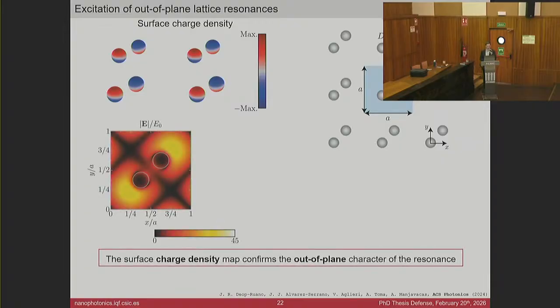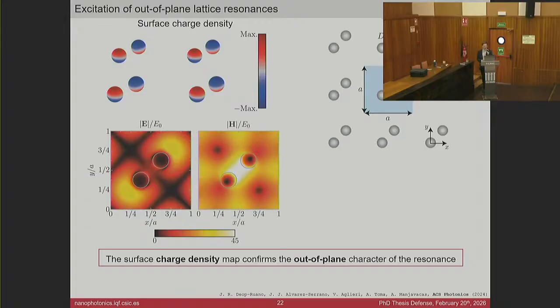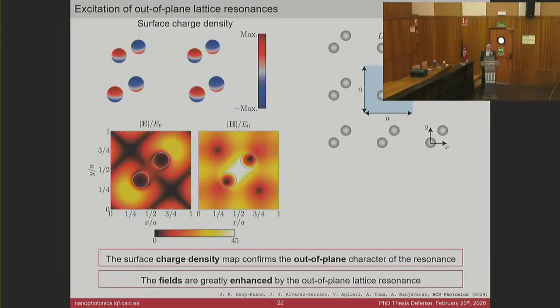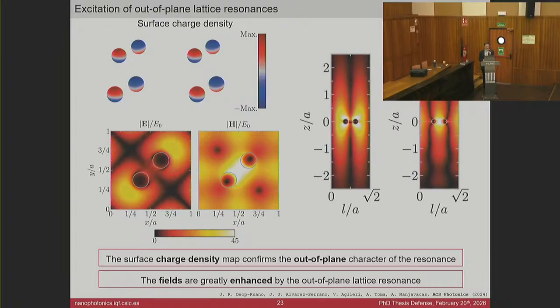I also use these finite element method simulations to study the electric field enhancement and also the magnetic field enhancement, and we can see that the fields are actually greatly enhanced around the whole unit cell. Because of this opposite orientation of the dipoles, in the case of the electric field this is minimized, but in the magnetic field it is maximized, and it actually attains really large values. We also observe that even if we move far away from the plane of the array, 2 periods, for example, we still observe a great enhancement.